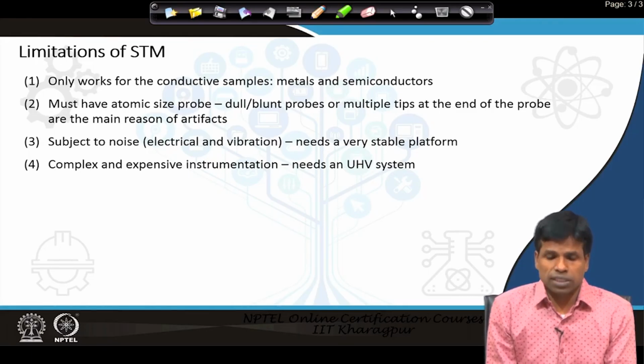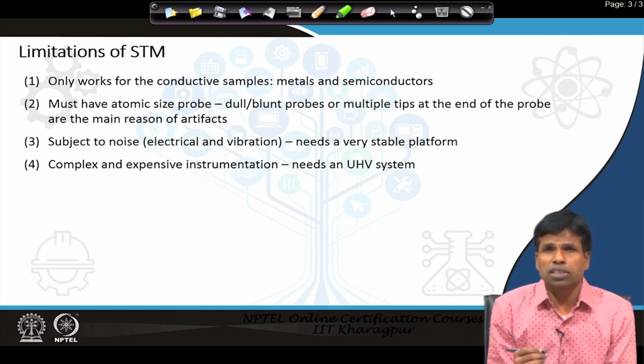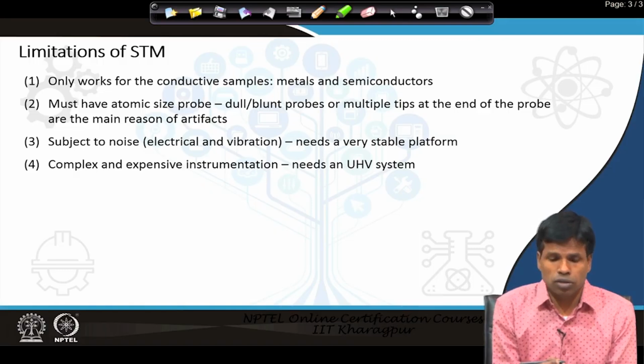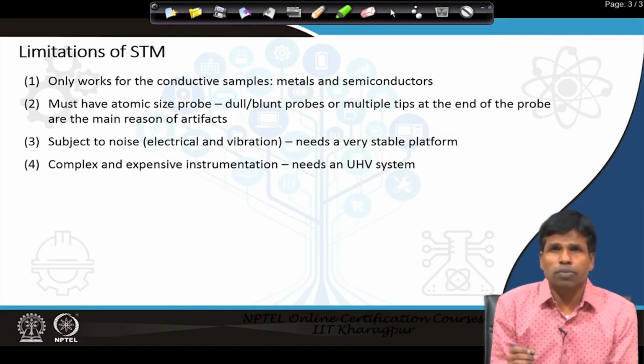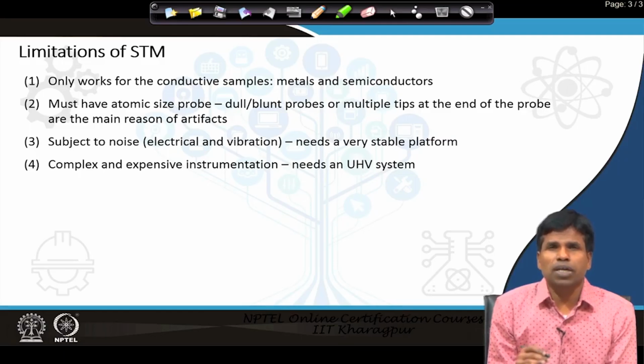Moreover, it has quite complex and expensive instrumentation. Practically it can be shown, but in order to really study the surface of a material, the surface has to be ultra clean, then only can we see the atoms of the real sample to be examined. If we take any sample to study under the microscope in any environment, the sample surface will automatically be contaminated in the environment, forming different types of layers, a few layers on the surface. Then we will actually be examining those contaminants on the surface rather than the real sample. So, most commonly STM is studied under an ultra high vacuum system or chamber.